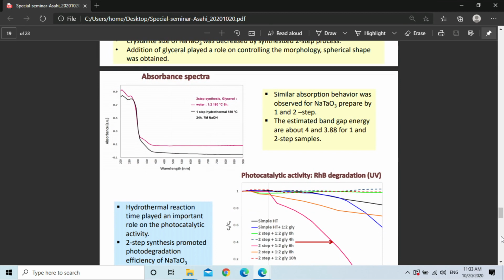For the absorbance spectrum, we also compare between one and two step. The two-step synthesis with smaller particles can shift the absorption edge to a red shift, which means a longer wavelength. It can respond more in longer wavelengths.